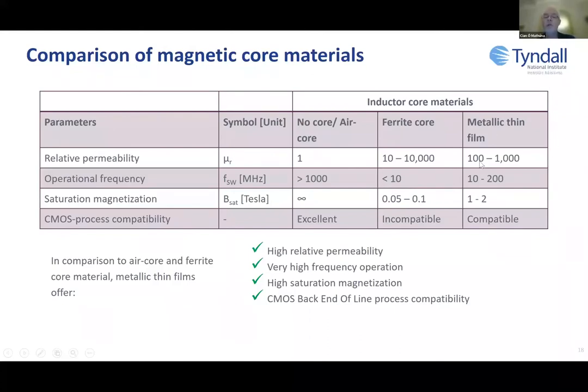Now, if we come to thin film, you can see we have reasonably good permeabilities to give us a good inductance value. We have the required frequency of operation that we're interested in. And we actually have very high saturation magnetization. So this means we can put a lot of current into these components, and they will still operate. The one thing about the thin film is it's compatible with silicon technology, which is really important. Whereas ferrite, at this moment in time, is not compatible with silicon technology, and therefore none of the companies in the semiconductor space will take up such a material.